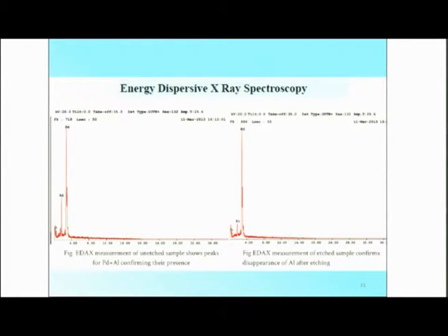and this is also shown up in this energy dispersive X-ray spectroscopy, where prior to the etching step, there is a huge presence of aluminum which goes away, and there is a presence of only palladium which comes out. Aluminum is gone completely because of the etching action. So this is before etching, and the XRD shown later on is after etching. So we are kind of sure that chemically aluminum is removed and there is porosity through the images, so it is the aluminum really which is getting removed. So that is conclusive out of these two experiments.